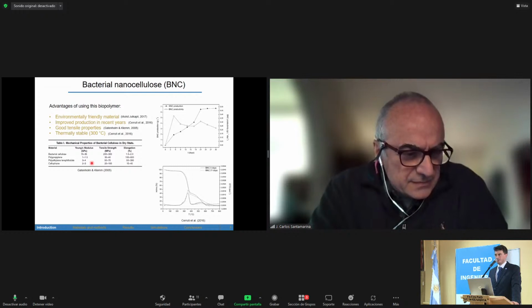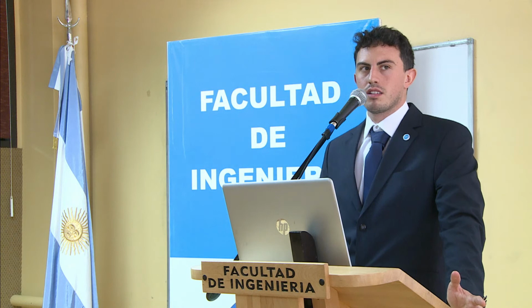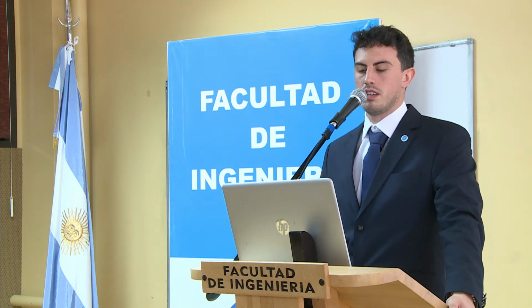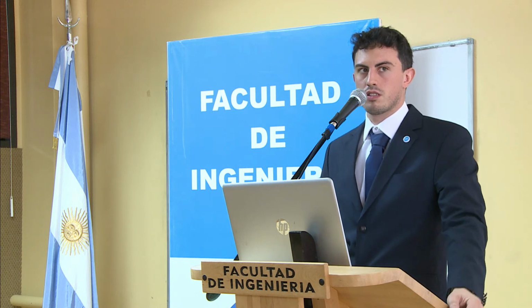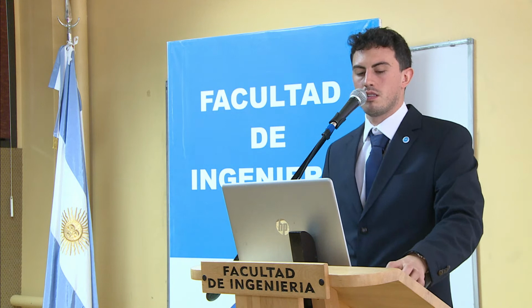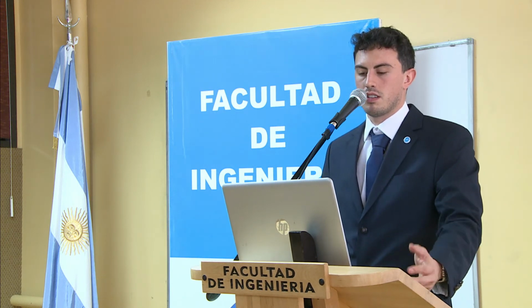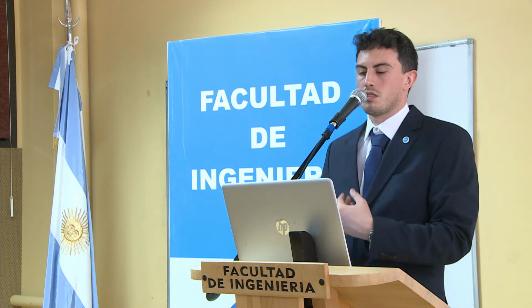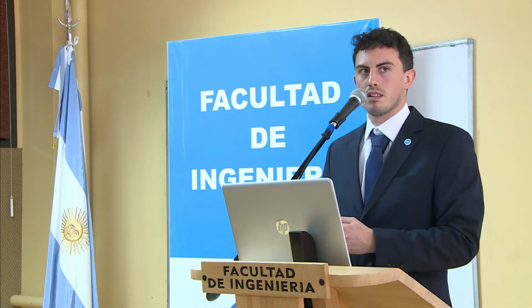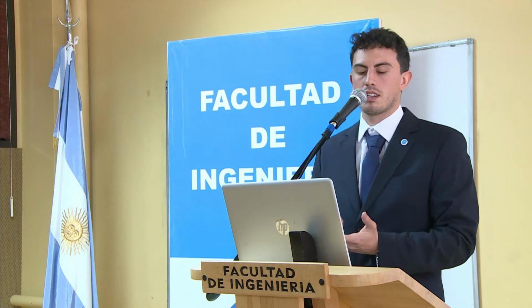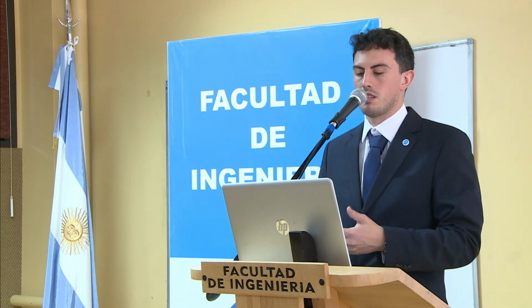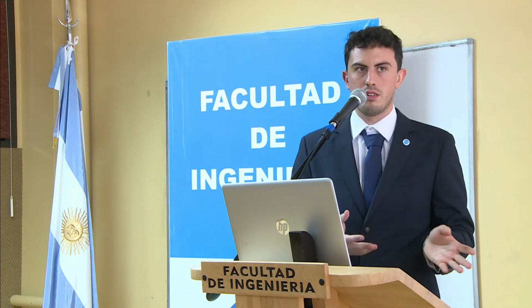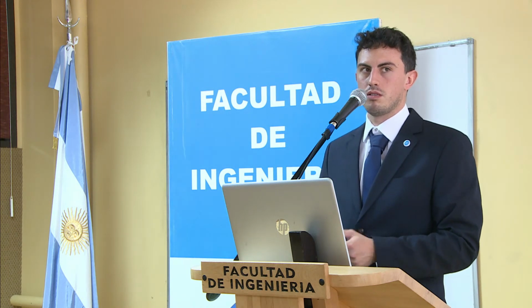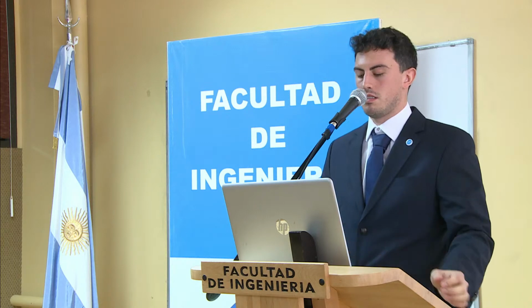Well, in this case, we talk about the physical changes produced by bacterial nanocellulose, but we didn't explore the chemical changes that it may produce on cement. So I think we need to first see how it modifies the chemistry in cement. But because we were seeing the large component, I mean, how it changes portlandite, how it increases hydration and everything, we think that actually it's in one part because it's a strong material and it has a large superficial area, but we also need to consider the chemical roles in play that we did not study in this thesis.